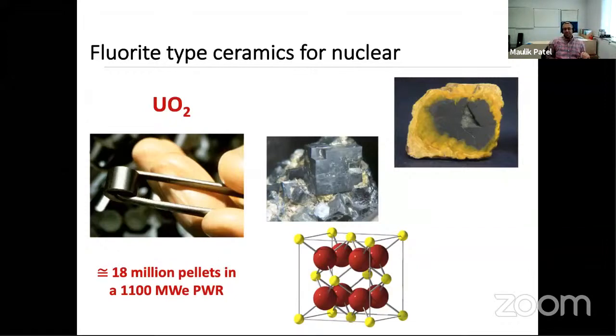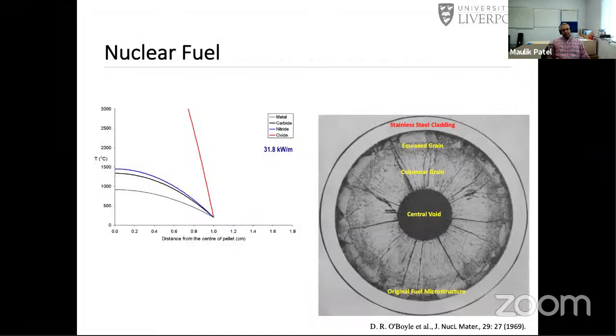So there are about 18 million pellets in a 1,000 megawatt electric power reactor. Just so you know, this is the scale at which we are looking when we talk about a typical power reactor. But the problem with the fuel is this: the best property you want in a nuclear fuel is obviously that it should fission, but in addition, since it's generating heat, it should be able to lose heat quite quickly. It means thermal conductivity should be extremely nice, and I don't know why, but we are stuck with uranium dioxide, which has one of the worst thermal conductivities of any material used in a nuclear reactor. There are historical reasons why, but we won't go into that. Just so you know, uranium dioxide has the worst property at which it is expected to be best.